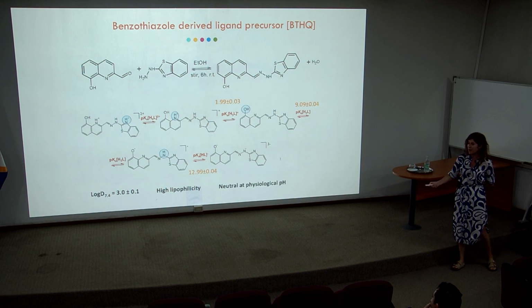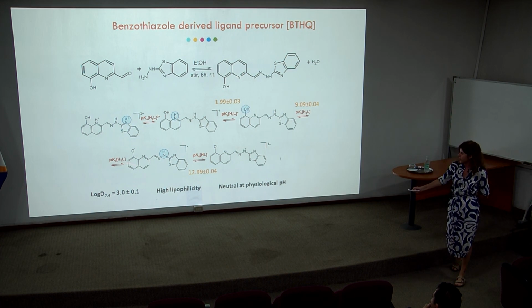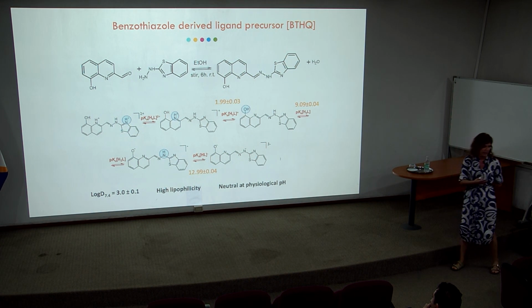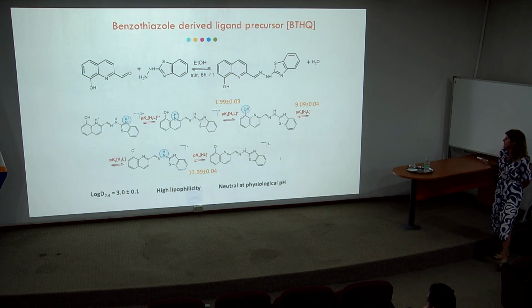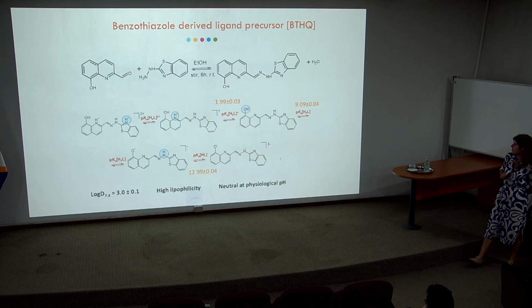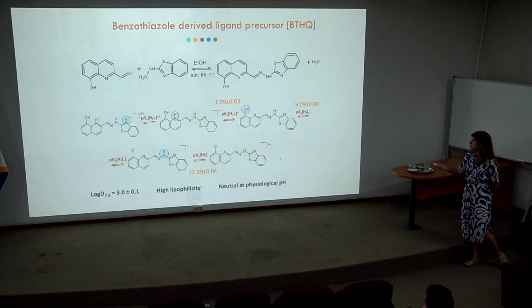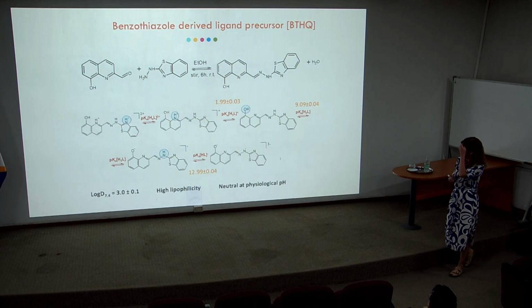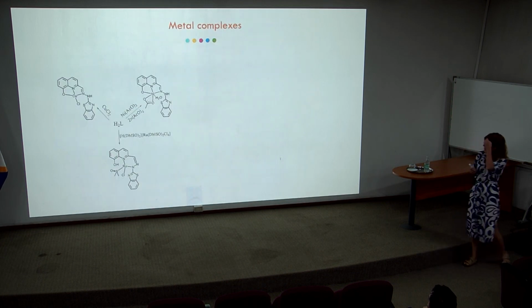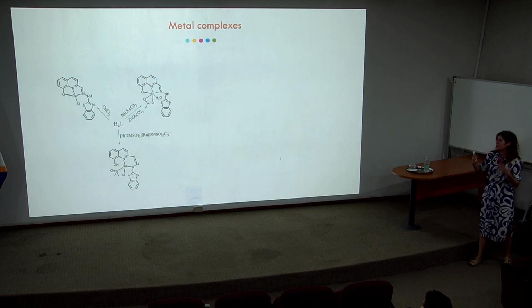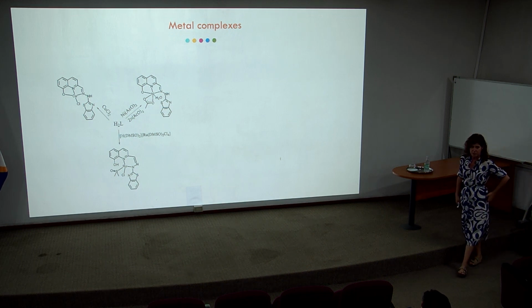The problem is that this ligand has a very high log D value, around 3, so it's very lipophilic, and neutral at physiological pH. This is the species that we will find in solutions at physiological pH. This ligand, as I told you, was complexed to a series of different metal ions.